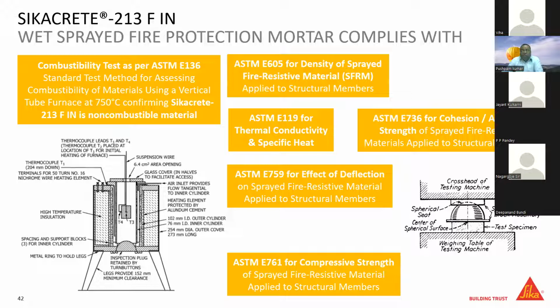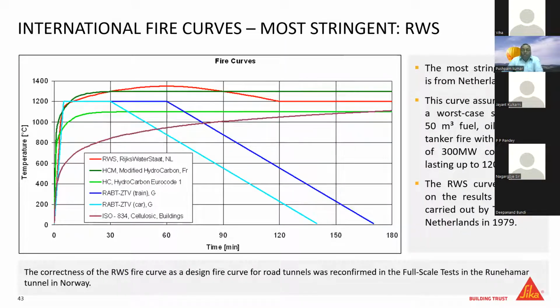There are various tests for which guidelines are defined, like ASTM codes, against which this test is done. One of the important tests is the RWS fire test. This is one of the tests designed for the worst case scenario, wherein 50 cubic meter of fuel is exposed to fire with a fire load of 300 megawatt. And this is done for more than 2 or 3 hours.